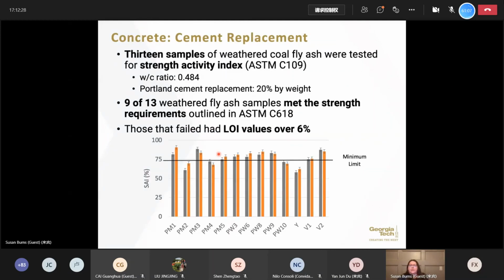And so what we did is we performed strength activity tests. Here we took 13 samples of the weathered fly ash. These are the ashes that were ponded for fairly long periods of time. And we used them as a cement replacement at 20% by weight. When we perform these tests, what you'll see is that 9 out of the 13 weathered fly ash samples that we tested met the strength requirement as outlined in ASTM C618. The remaining samples that failed had very high LOI values, over 6%, which violates the ASTM standard.